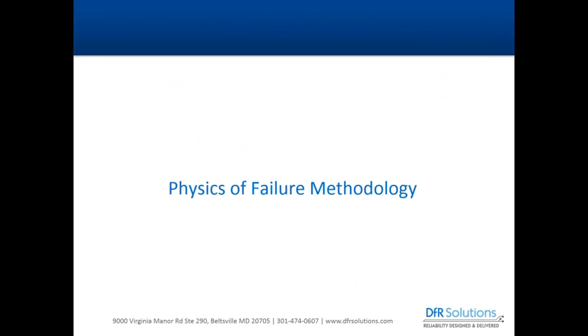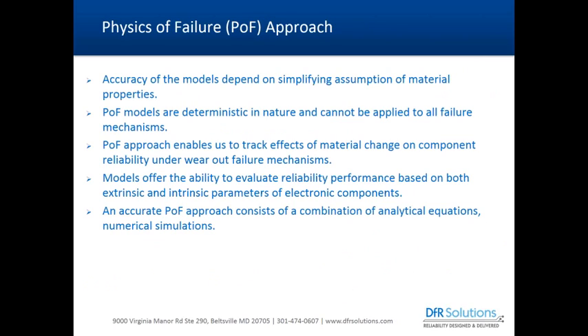Now we transition to physics of failure methodology and why it is critical in predicting solder joint fatigue from system-level effects. The accuracy of any simulation — whether finite element or physics of failure using analytical equations and empirical models — depends on your constitutive model. Defining the right material properties and solder alloy properties is critical to understanding what's happening in those solder joints. You also need the empirical aspect to deterministically associate solder joint mechanics to cycles to failure, driven by accurately predicting the failure mechanism or mode.